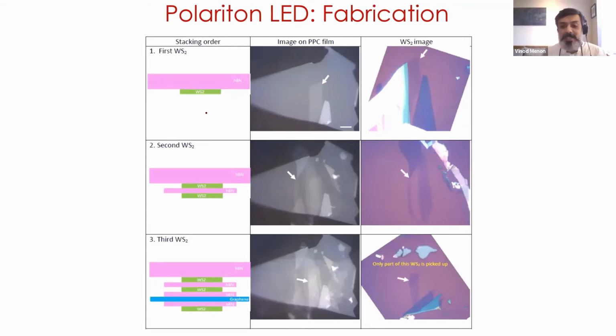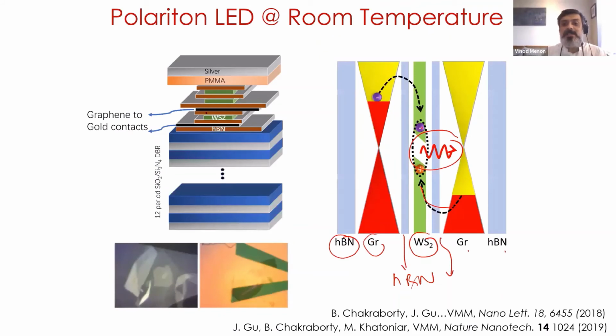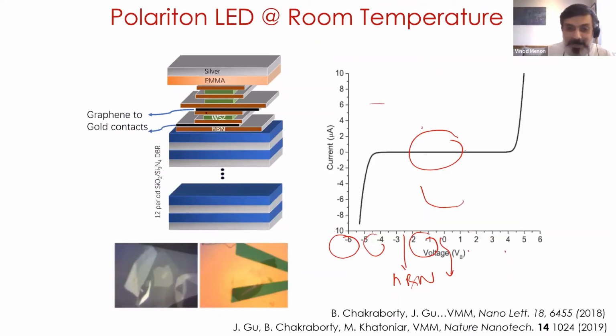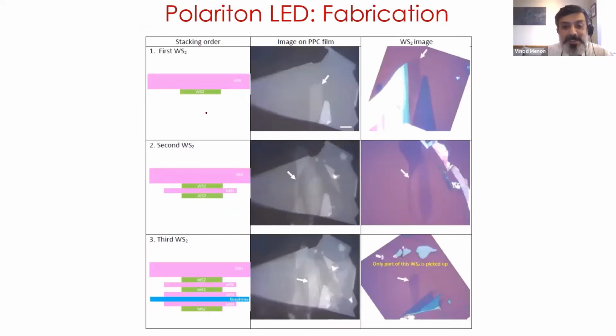To me, it's fascinating that you can actually make a tunnel device with this Scotch tape technique, and it actually works. So the whole thing is done with exfoliation. The key here is that if you're making an electrically driven device, you need to have it in such a way that there is current flowing through the entire system, which means there needs to be overlap between the different layers. And of course, there are techniques for this, like registering the different layers and making sure that one is on top of the other and so on.